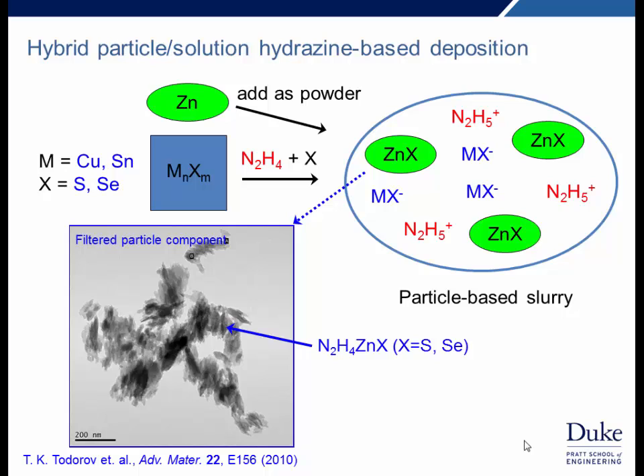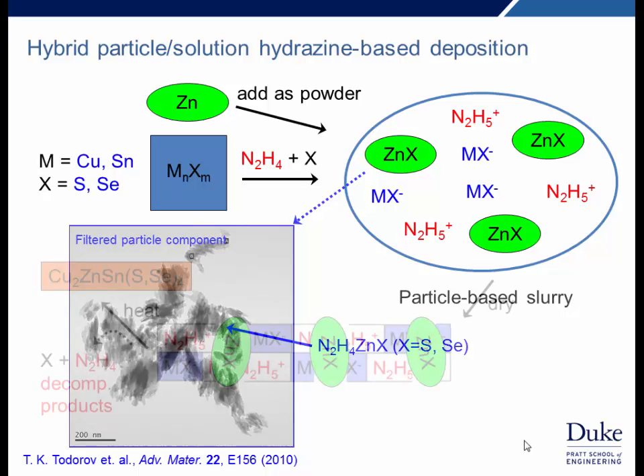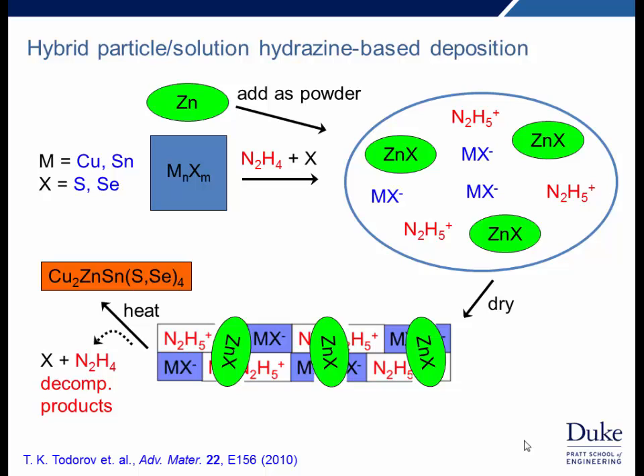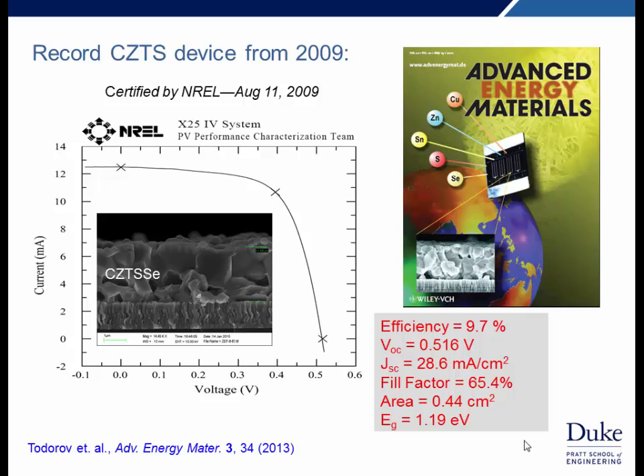And you can see what those look like here. These turn out to be hydrazine zinc chalcogenide, which easily decomposes to the corresponding zinc chalcogenide under gentle heating. And so if we take this slurry, we can process it using the same types of approaches we use for the pure solution, and we generate, after heating, our CZTS film.